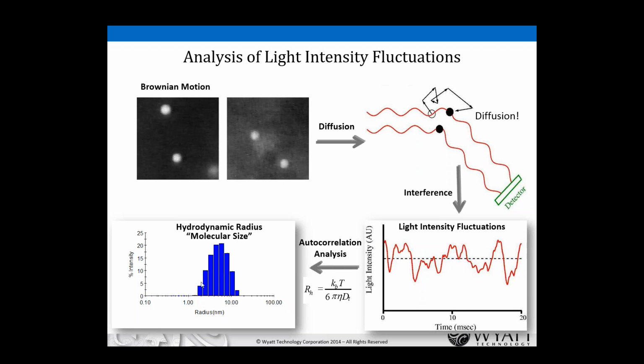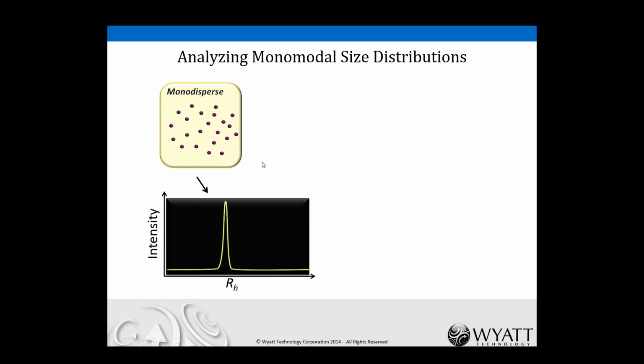One of the beautiful things about dynamic light scattering is that even without a preliminary separation technique, you can get a rough idea of the distributions of sizes in solution. So you can have a single sample, shine the laser into it, and if that sample has multiple size particles present, you'll get a distribution of sizes. The resolution on size is not great. We'll discuss that a little bit later on, but as you can see in the graph here, we can apply analysis that gives us a distribution of sizes. And so then this, as applied in the DynaPro plate reader, which I'll bring up shortly, you can apply this analysis to all the different wells in a microwell plate and rapidly assess the presence of aggregation in those different samples rapidly.